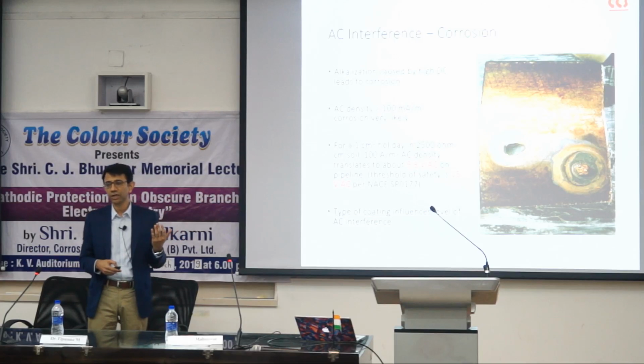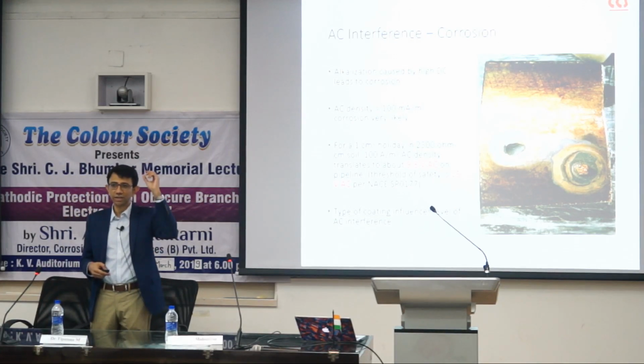And the reason for that is simple. A polyethylene coated pipeline has a very high electrical resistance, maybe of the order of 300,000 to 500,000 ohm meter square. And because of this high degree of isolation between the pipe and the earth, obviously the electrical induction because of AC is very high. At an AC density on the pipeline greater than 100 amps per meter square, the corrosion is very likely.